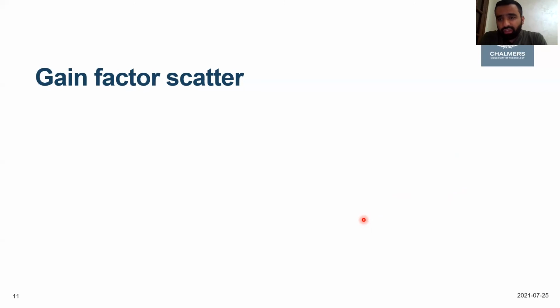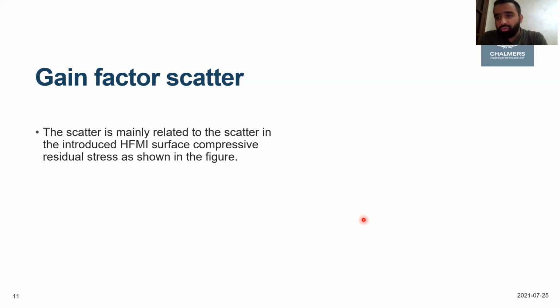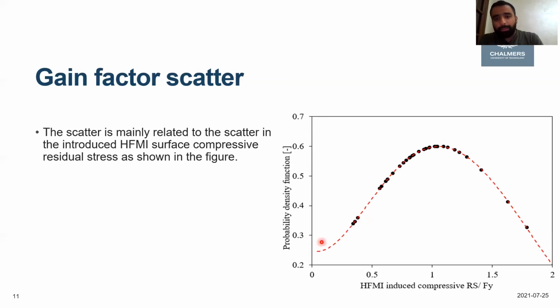But we got a lot of scatter in the gain factor, as you saw in these 3 figures. This is related to 2 different factors. One is the scatter or variability in the introduced surface residual stresses, as you can see in the figure. On the x-axis you have the ratio of the introduced compressive residual stress at the surface divided by the steel quality, and you can see that this ratio varies between 0.4 and almost 1.7. That's a lot of scatter, which will be reflected in how much we gain from HFMI treatment. But it's always good. It's only a matter of how good.